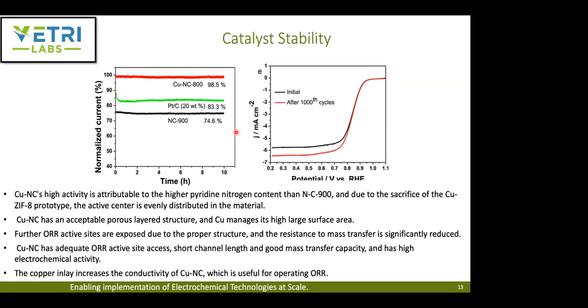And the CuNC has an acceptable porous layer structure, and the copper manages its large surface area. Because of this porous structure with micropores and mesopores, you have both exposed ORR sites and also a better mass transfer. And then the copper nitrogen doped carbon has adequate ORR active sites with a shorter channel length, and it also has a good mass transfer capacity with high electrochemical activity. Also, the presence of copper indeed increases the conductivity of the overall catalyst, which is very good for operating your ORR process.